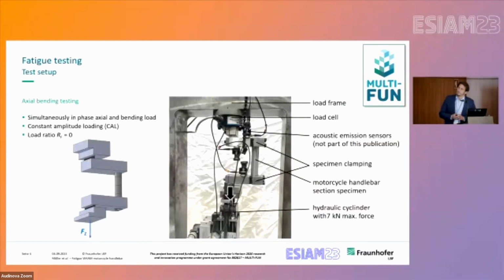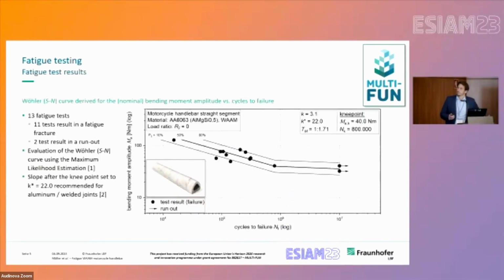Therefore, we set up a fatigue test, which is a combination of simultaneously axial and bending loading. So we have here a lever arm included in an axial fatigue test rig, so that later on we have a maximum stress at the inner side of this specimen, which is again not a circular shape, so that it is pronounced to one specific region. The test setup itself consists of a load frame, load cell, nothing spectacular, except maybe these acoustic emission sensors, which are not part of this presentation. We have clamping of the specimen and a hydraulic cylinder for actuation, and the load ratio was pulsating loading, R equals 0, under constant amplitude loading.